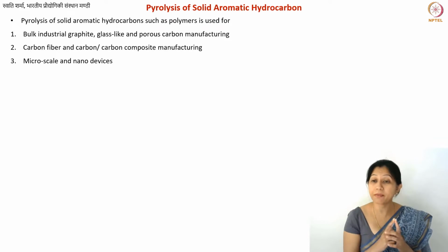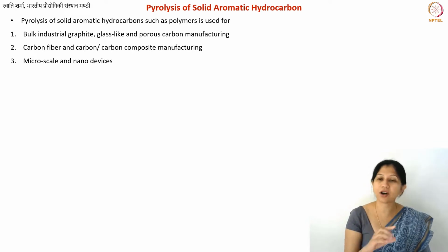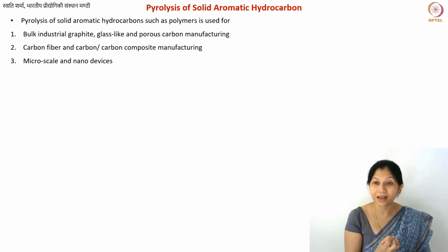However, the important thing is that their pyrolysis, their thermal decomposition, depends not on the photoinitiator but on the skeleton, your primary polymeric structure. So the byproducts you get from pyrolysis of phenol-formaldehyde resin at large scale, if you use the same or a very similar resin at small scale with the photoinitiator, the pyrolysis mechanism will still be guided by the chemical structure and not by the photoinitiator structure.